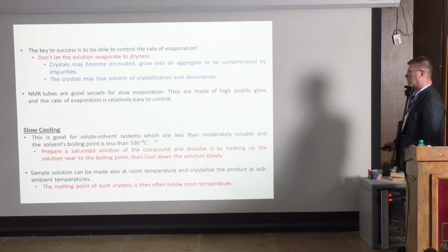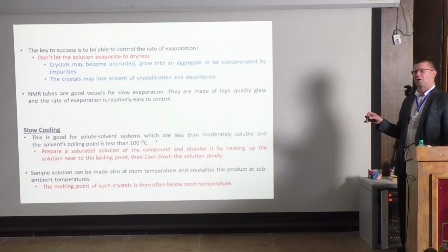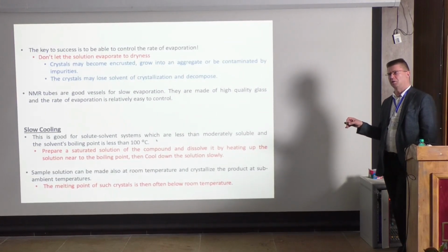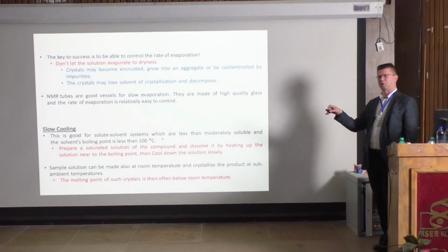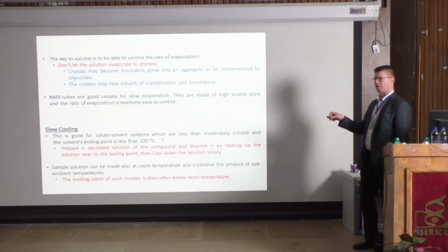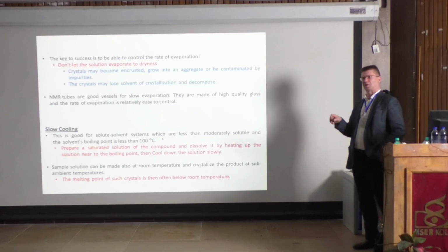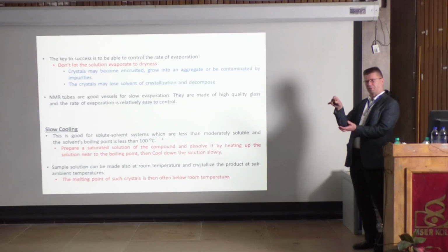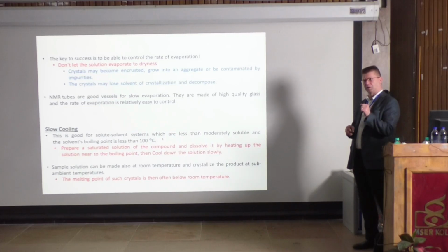So the point in there is that you can also do it in a different way, that you start from the room temperature and you put it in the deep freeze. So you go from 25 to minus 20, and then the crystals grow when you go, let's say, to minus 10. But now there is the difficulty with this. Because if you now take that tube where you crystallize the vessel to the room temperature, it will dissolve back.